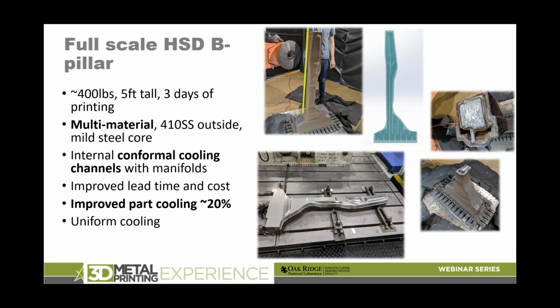This little slug of material in the middle is a demonstration of how we wanted to just print the skin, basically, and then backfill with a casting to give it some strength in the middle. But overall, we were able to reduce the amount of time it took. This only took 3 days of printing and then a few days of machining. And we improved the part cooling by 20%. That's something that always kind of comes as a surprise, but then not as a surprise. Not only can we improve the manufacturing of this thing and make it cheaper, we can also improve the performance. So that's always an added bonus when you're going with additive, especially for these heat exchange type situations.